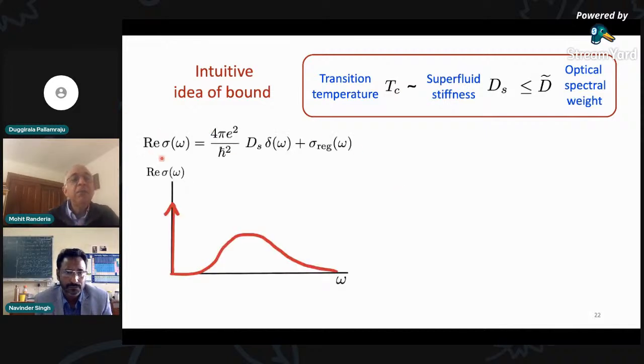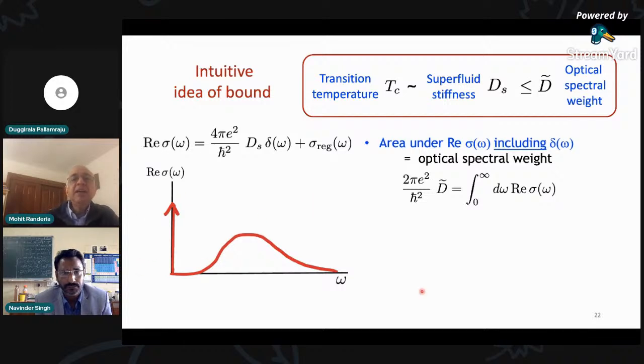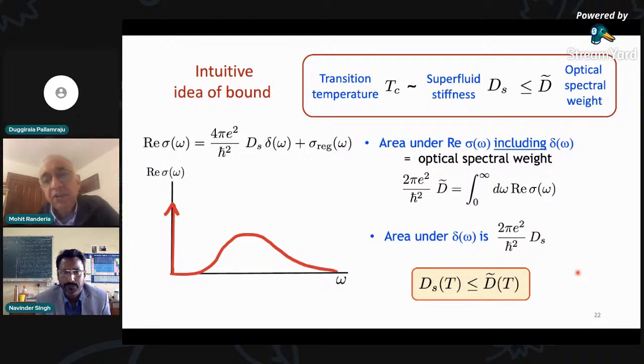I already told you that the optical conductivity has a delta function peak at the origin, whose strength is the superfluid stiffness. So the total area under the optical spectral weight, the integral from 0 plus to infinity, where the delta function is counted with half, of the real part of sigma omega, including the delta function or half of it, is what is called the optical spectral weight D tilde. That's the definition. Whereas the area under the delta function is just Ds. So of course, the total area, including the delta function, has to be larger than the delta function. So therefore, the optical spectral weight D tilde is an upper bound on Ds.